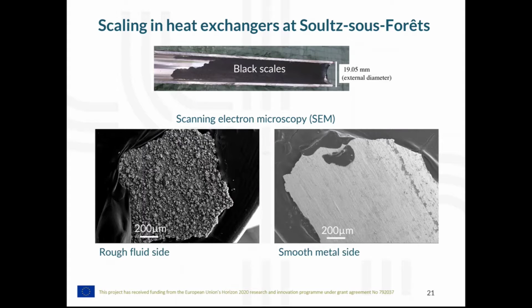Okay, here is what the scales look like. In fact, normally from the brine, these are sulfates that precipitate, mostly barite sulfates, but inhibitors are used to reduce the amount of scales, and then sulfide scales precipitate. So they occur as black scales, and on the lower part of the figure, you can see scanning electron microscopic views of the scales. On the left, the rough fluid side, so the side of the scale in contact with the fluid, and on the right part, it is smooth when it is in contact with the metal.